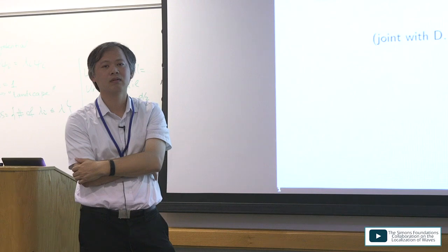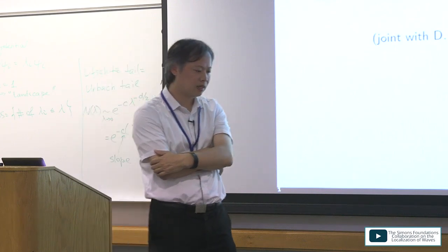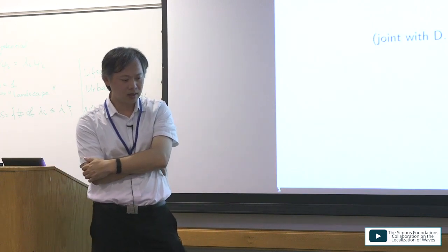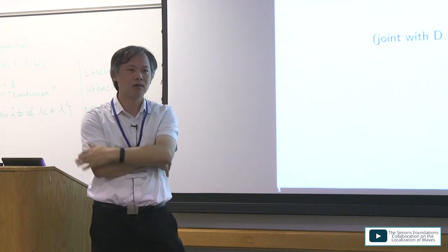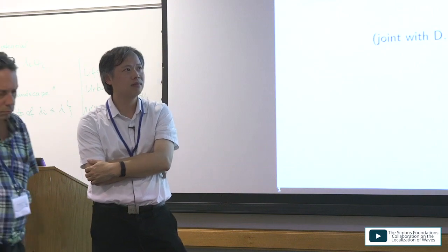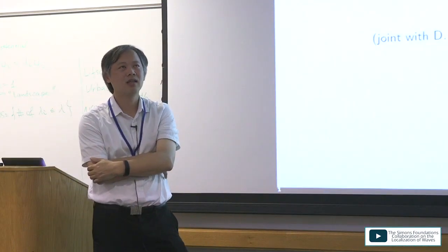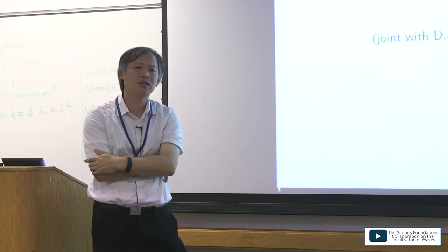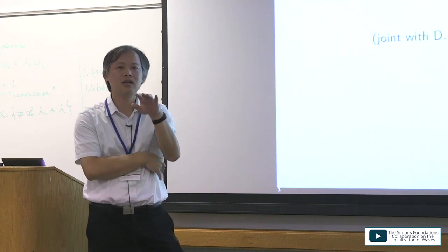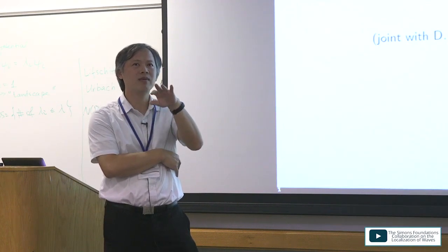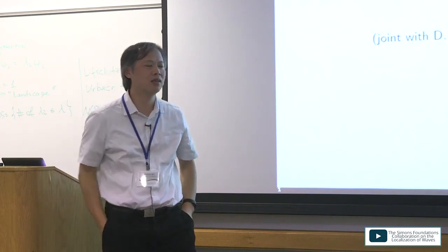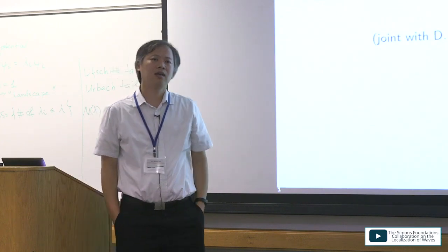And what is the criterion for that? I think if you consider the wave function, then you need to consider the effective mass. For aluminum gallium nitride, the effective mass is still high for holes, and for electrons it's a little bit increased compared to gallium nitride. Gallium nitride is 0.2, and I remember aluminum nitride is 0.3. So I think it's a similar order. A little bit of adjustment may be needed, but we didn't test that case.